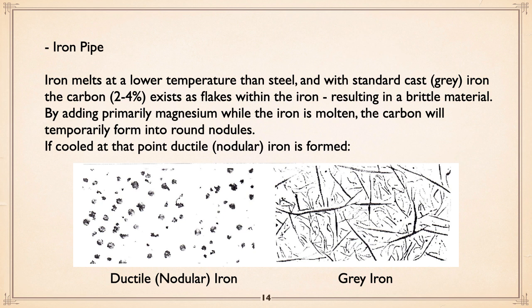So if it wants to crack, it will follow a line of carbon, which is why if you break cast iron, and it doesn't take much to, you virtually can't bend it, hardly any at all before it'll break. You'll notice it looks sparkly. That's because you're looking at all these carbon flakes. Now, by adding primarily magnesium while the iron is molten, the carbon will temporarily form into round nodules. If cooled at that point, ductile or nodular iron is formed.